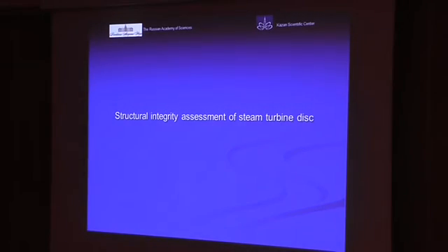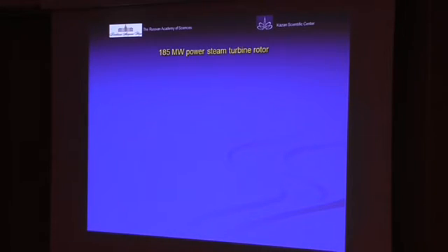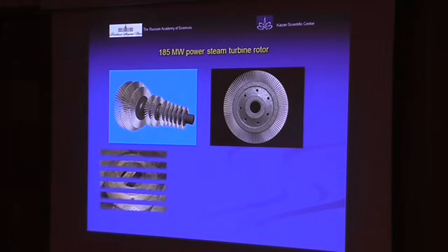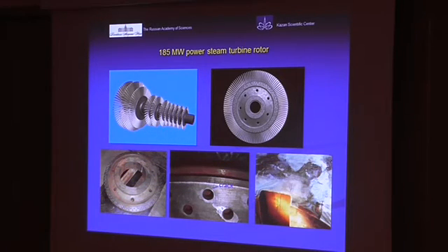So, the last point of my presentation is the application of plastic stress intensity factor to the structural integrity of a turbine disk. The subject of our consideration is a disk with some loading history. At operation, we have found a quarter elliptical surface crack in slot fillets in a half of the wheels.